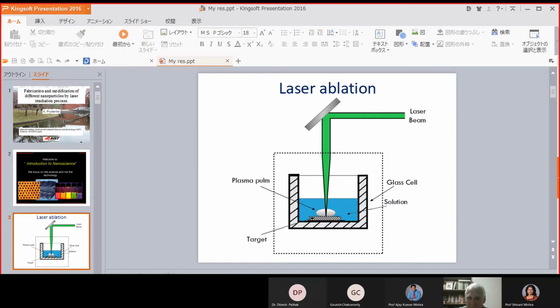After 1 hour of heating, of boiling, we saw that our colloid changed color. First it became transparent, no color, and finally it became the typical silver color, reddish or yellow reddish. So we were sure that it was silver nanoparticles, but when we checked our result by electron microscope, we saw this result again was not so beautiful. We produced some huge particles with a size of about 100 nanometers, and these huge particles had different shapes, not spherical particles, of course.